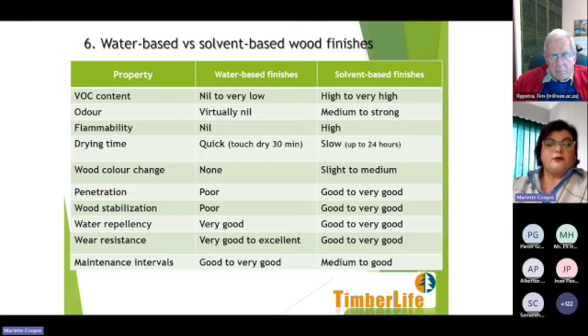If you talk about penetration into the wood surface, water-based finishes have a limited one. In other words, it's more a layer forming on top of the wood surface, whereas solvent-based finishes, depending on the type of product, being an oil or a varnish, will have good to very good penetration into the wood surface. When we talk about stabilizing the wood structure, the inner structure of the timber, with water-based finishes, it's poor because it's mainly a film forming or sits on top of the timber, and solvent-based finishes are better because it does give you penetration and it actually fills some of the wood cells below the surface.